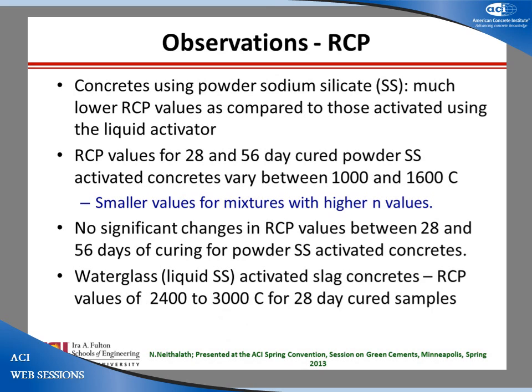So here are the observations which I just told you about already. The important one is that there is no significant change when you have powder activation between 28 and 56 days. It doesn't seem to do anything further. The same trend was seen in the compressive strength results also.